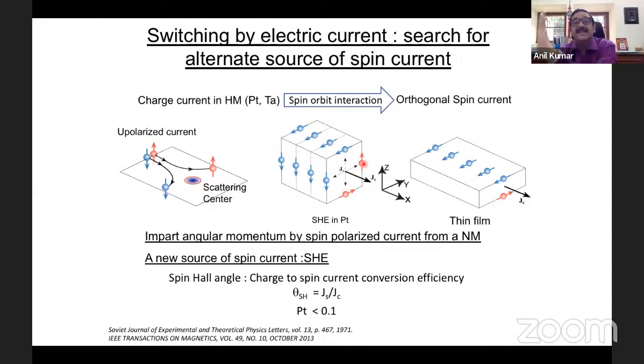One type on the side surface, the opposite on the other side. Now, this material, instead of a three-dimensional structure, if I make it two-dimensional, a thin film, what happens? If I pass electrical current, one type of spins will get accumulated on the top surface, and the other opposite type of spins will get accumulated at the bottom surface. And then the efficiency of this is called the spin Hall angle. That means the spin Hall angle is the amount of spin current you have generated divided by the charge current.